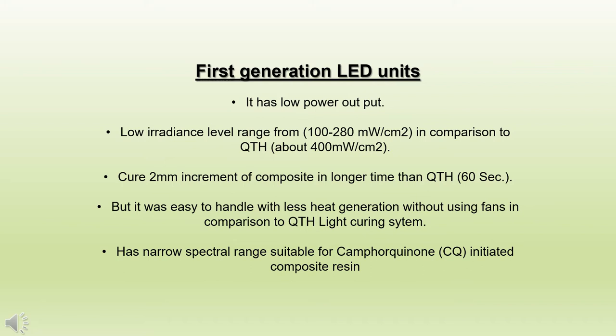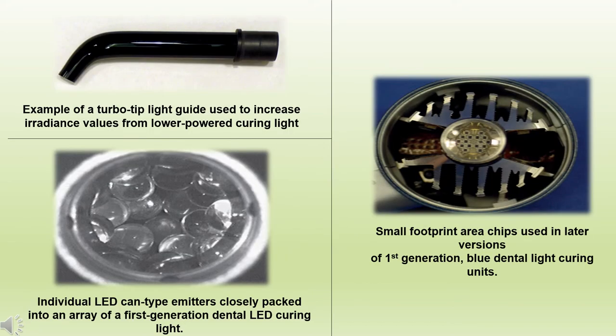It cures 2 millimeter increments of composite in longer time than the QTH, which takes 60 seconds. But it was easy to handle with less heat generation without using fans in comparison to the QTH light curing system. It has a narrow spectral range suitable for camphoroquinone CQ initiated composite resin. These units have an irradiance increasing turbo tip, 5 mm cans, and the array is typically from 8 to 64 in number of LEDs.